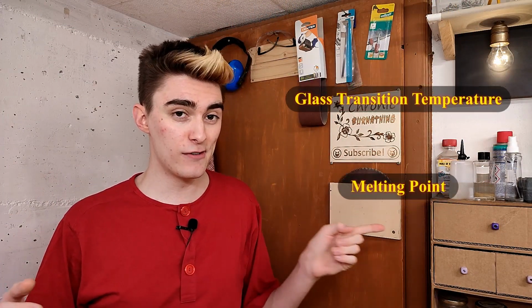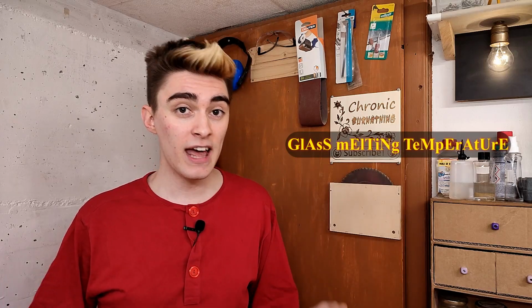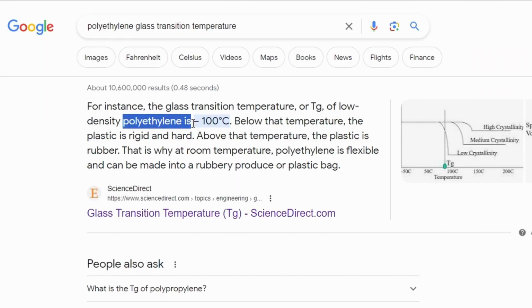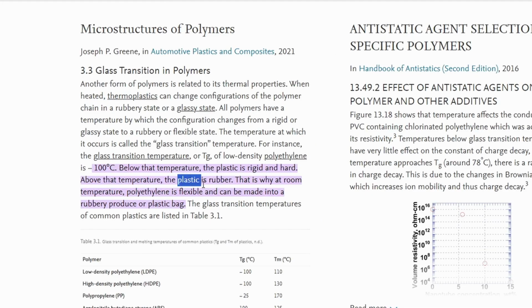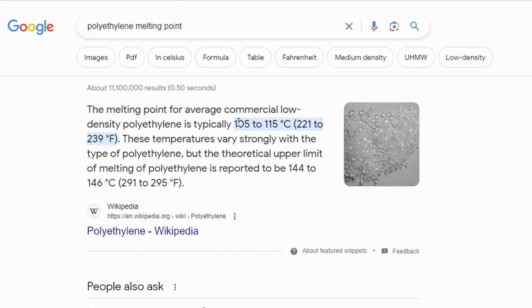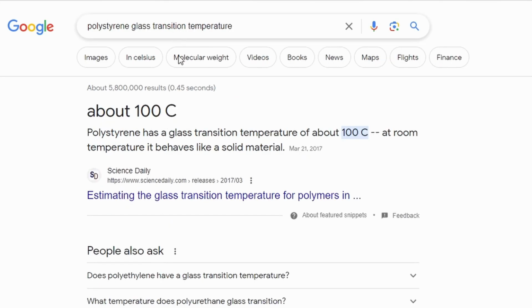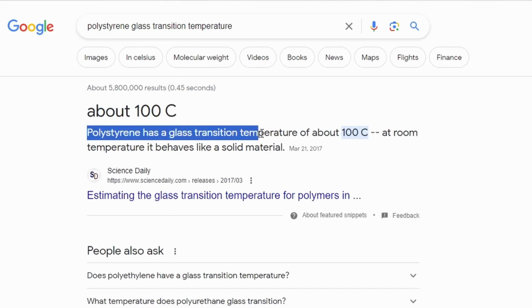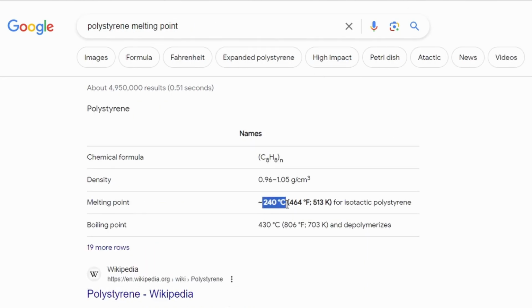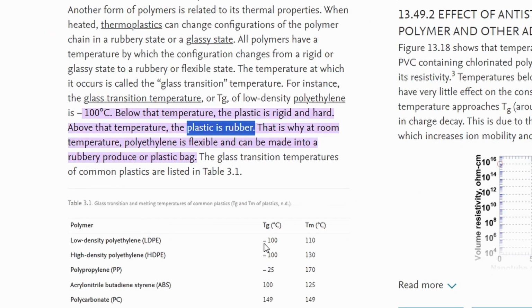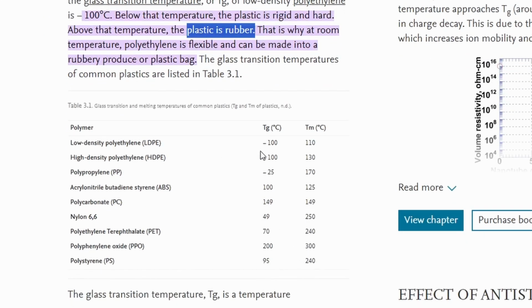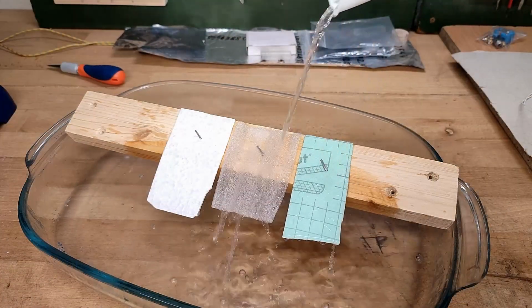It means I apparently got glass transition temperature and melting point mixed up in a sloppy Google search earlier. It appears polyethylene, with its glass transition temperature of -100 Celsius, is doomed to an internal state of gumminess unless you melt it at +120 degrees, whereas polystyrene is always below its glass transition temperature of +100 C and only starts to melt at around 240 degrees. That's why polystyrene as a plastic is quite brittle as opposed to polyethylene and polypropylene, which in turn nicely matches the results I got with my torture test.